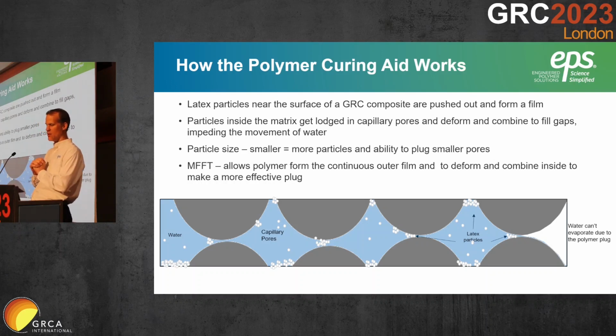In addition to that, you've got particles inside the matrix that get trapped and lodged in these capillary pores, in the smaller places, as water comes and evaporates out. Again, the water can get out, the polymer can't, and it gets stuck in there because of the MFFT, minimum film formation temperature, which basically means that at any temperature above that, these particles can coalesce and form a film. Because of that property, they come together and form essentially a plug that retards the movement of the water. So water outside can evaporate, but it keeps most of the water inside, allowing it to hydrate.